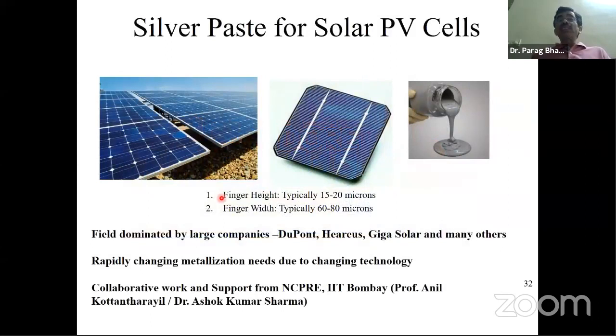Now, another very interesting opportunity. It's a big opportunity. All of you are aware of solar cells. When you look at solar cells very closely, you will see all these lines running on the top of each cell, right? What are these lines? These lines are basically made from silver, from a special kind of silver paste, and you heat treat them. But basically this silver makes contact with the wafer, and this is how you collect your charge carriers, or the power out. If this silver contact was not made, you would not get the power. So it's a very important product, and if the quality of the paste is right, and contact is made correctly, then you would get the right kind of efficiency. Only thing is, this is a very challenging opportunity.